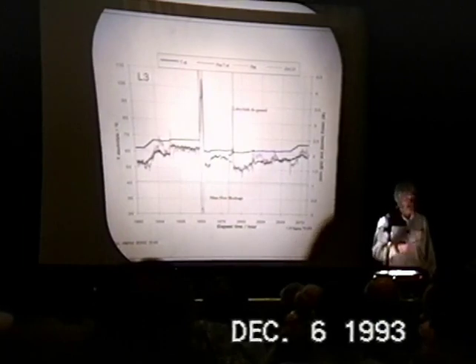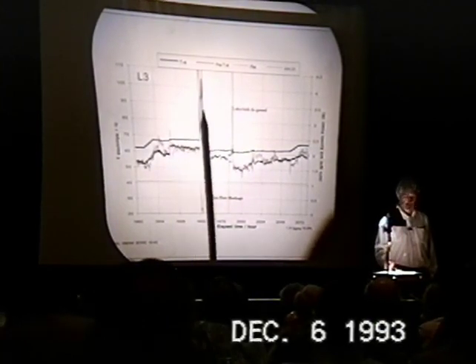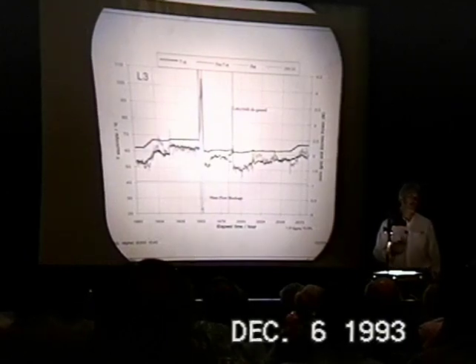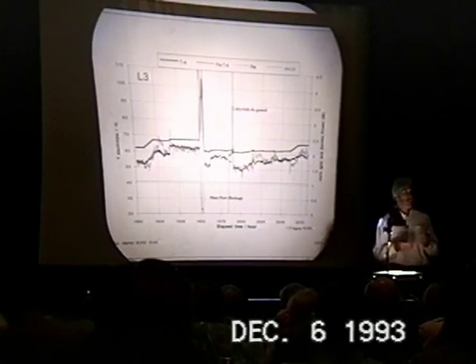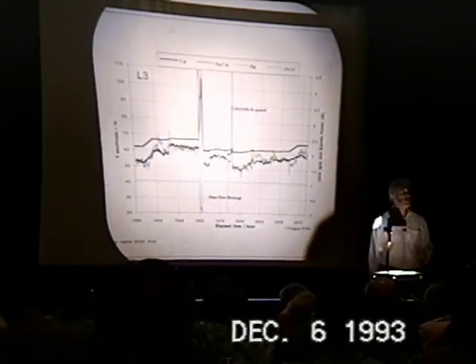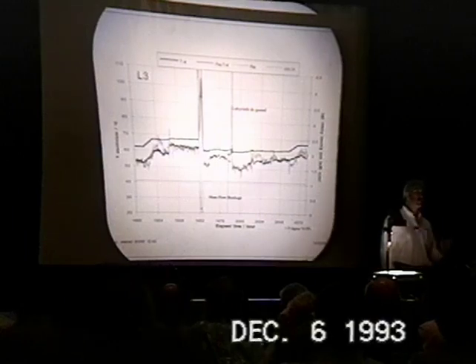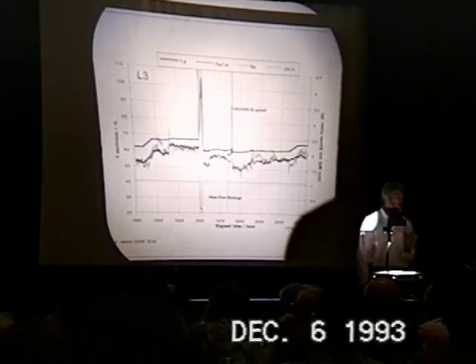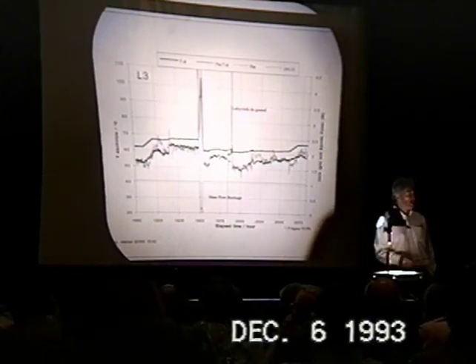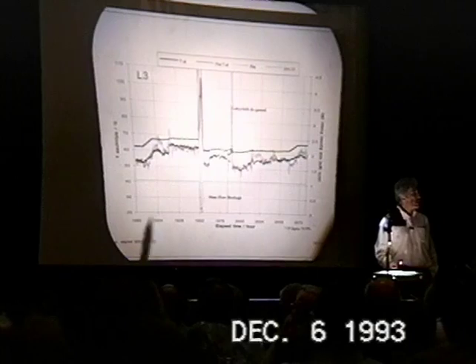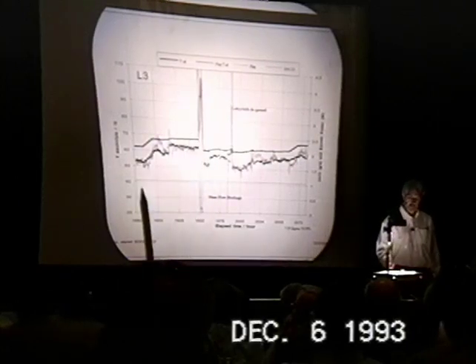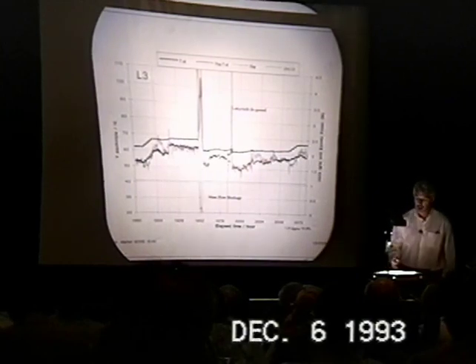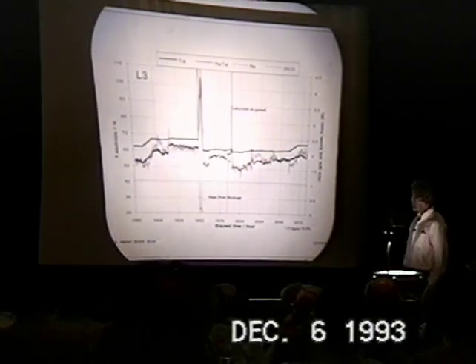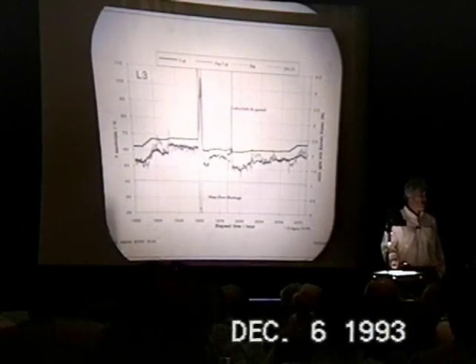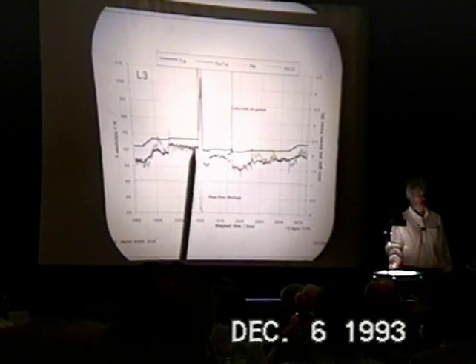We're saved a little bit in the fact that we were recording the electrolyte temperature, that is the blue line. We can calculate in some sort of isoperibolic mode what the power generation rate inside the cell was by knowing what the temperature of its boundary is and what the temperature of the electrolyte is. So I have a crude isoperibolic calorimeter which I can use to calculate the power and maybe retrieve the missing information. Here is the calculation shown in green superimposed upon the calculation from the mass flow rate. They superimpose approximately, giving me confidence that this calculation of power is at least reasonably accurate.